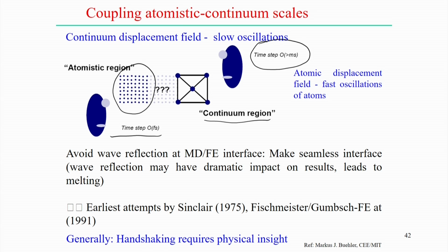Now, how can we link these two scales through the multiscale modeling approach? Normally, we avoid wave reflection at the interface between the molecular dynamics level and the finite element level. It is possible to make a seamless interface, because wave reflection may have a dramatic impact on the results; sometimes it leads to melting. So, making a seamless interface is probably the one challenge for the multiscale modeling approach.